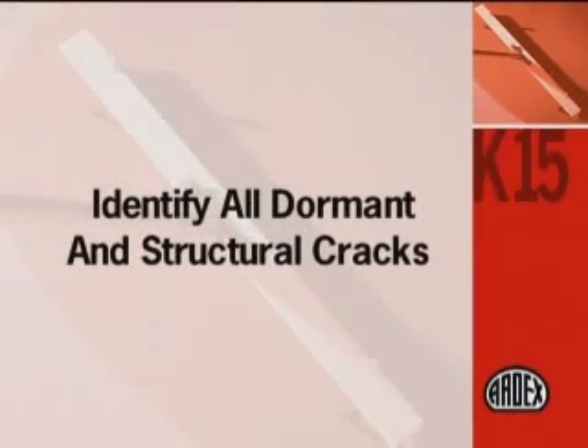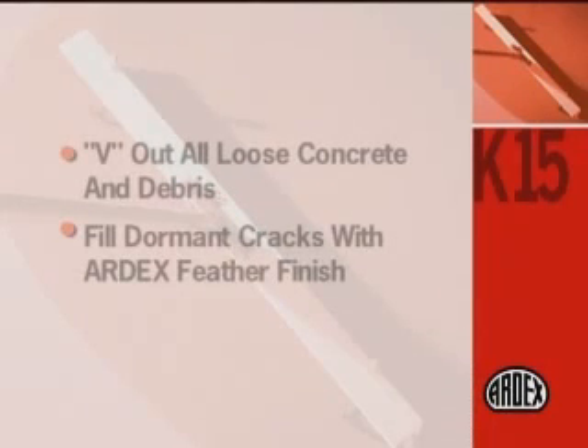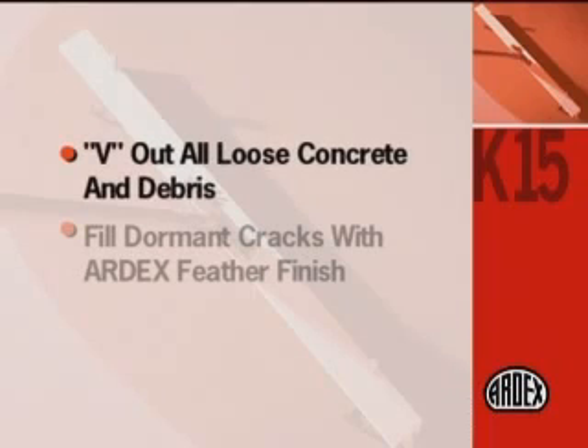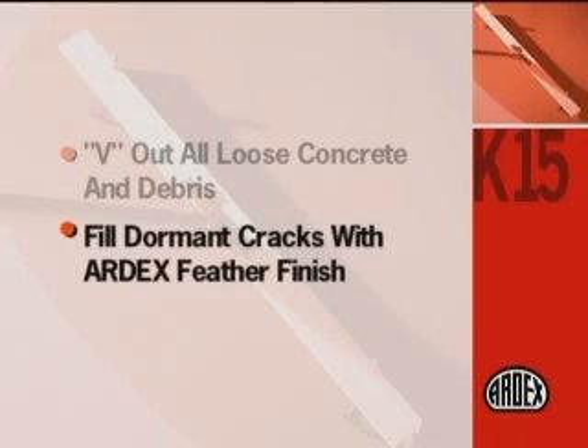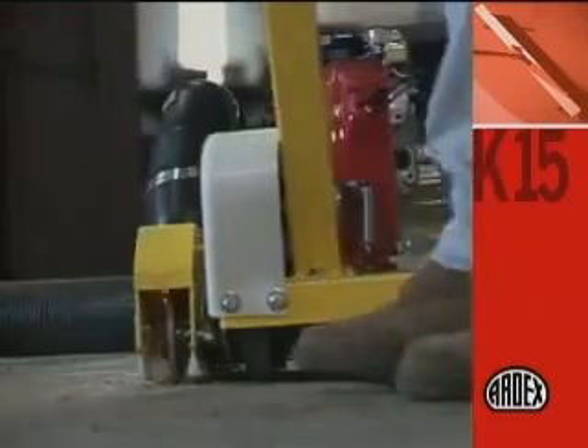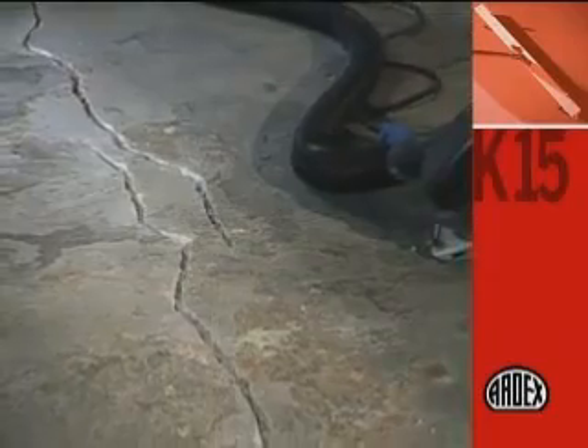It is important to differentiate dormant cracks from active or structural cracks prior to the installation of ARDEX K15. When in doubt, seek the advice of a structural engineer before proceeding. A dormant crack may be filled with ARDEX feather finish after V'ing out any loose concrete and debris. If a dormant crack proceeds to exhibit movement, it will telegraph up through the patching material, creating a flaw in the finished floor covering.